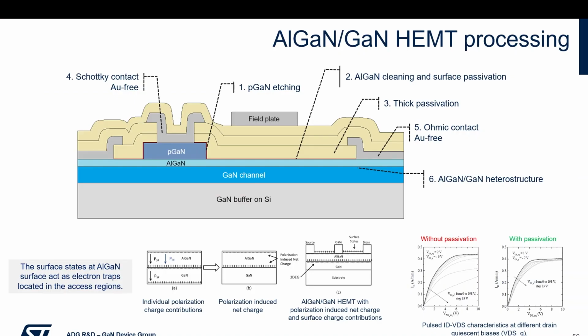Again, what do we need to pay? Well, when you look at the structure, there are a couple of things. The first thing that I will mention is epitaxy. You grow this on a wafer of silicon, and of course there is a large mismatch in the lattice between the GaN and the silicon, and you have a large mismatch as well in the CTE. So whenever you go to high temperature and then go down, there is a lot of stress. So you have to manage your epitaxy in such a way that you have something which is flat enough at the end of the day to be able to go through the existing line. And there is a variety of other things that concern the way in which you control the properties of this surface, and avoid introducing traps by the process itself. So the way in which you passivate the surface and etch the surface is particularly important. I would say that these are the two main points: the way in which you control that you have low defects at this interface or low electric field at this, and the way you manage your epitaxy.